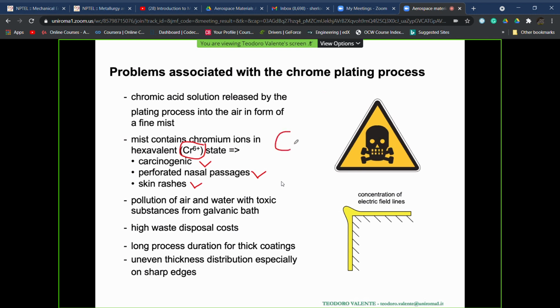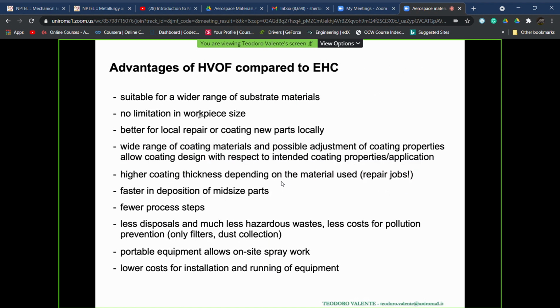And there were some experiments based on the same principles, but using not hexavalent chromium, instead using trivalent chromium, but the performance, or well, let me say better, the properties of the coatings fabricated in this way were not essentially comparable to those obtained by the use of hexavalent chromium. And one solution to chromium plating based on hexavalent chromium is to refer to the use of HVOF coatings.